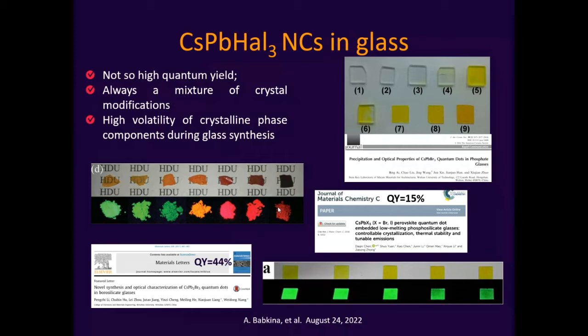But as you can see also on the slide, in this picture, you see that the glasses are very strange, you know? They are not really transparent, and sometimes they don't look like glass, and authors even grind them to make a powder. It's really very strange for all glass makers, because when you synthesize a glass, the first thing that you should do is to make a photo of it to prove that it is really glass, it is really transparent, and it is a glass that you can hold in your arms, and it will not melt in them, you know.